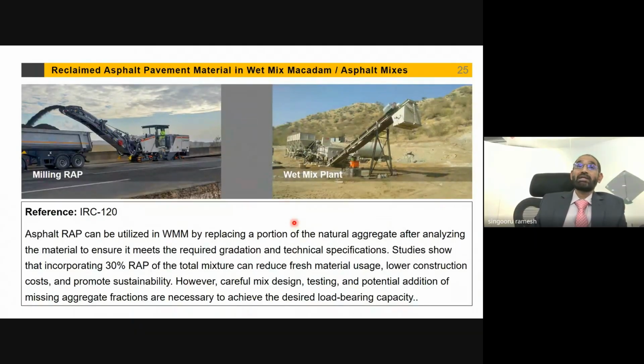Studies show that incorporating 30% RAP of the total mixture can reduce fresh material usage, lower construction costs, and promote sustainability. However, careful mix design, testing, and potential addition of missing aggregate fractions are necessary to achieve the desired load-bearing capacity.